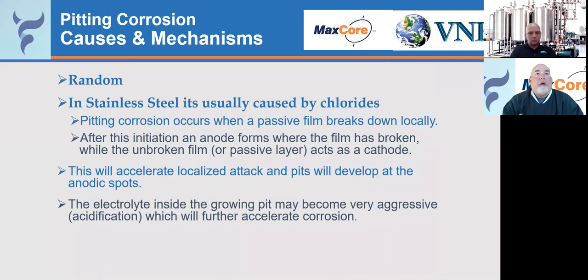Pitting is something that is very random. In stainless steel, it usually is caused by chlorides. And in our particular cases, a lot of times high buffer solutions that we use with high chloride contents can also be caused by cleaning solutions, which have certain chlorides involved. You start thinking about bleach and those types of things that a lot of places use for cleaning. That's chlorine. So you have to stop and think about what that is. Pitting occurs when the passive film breaks down locally. And after the initiation, an anode forms where that film has broken and you have an unpassive surface there that takes place.